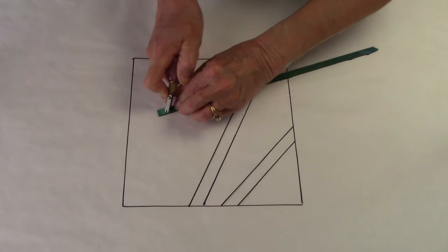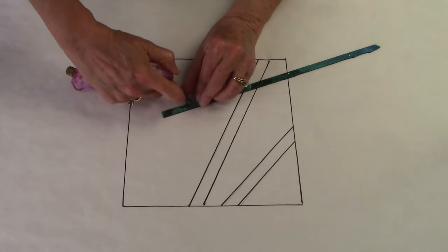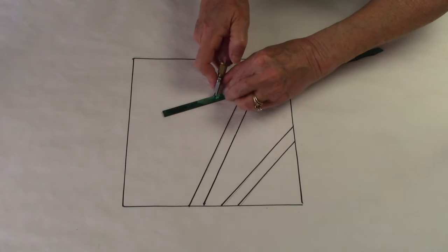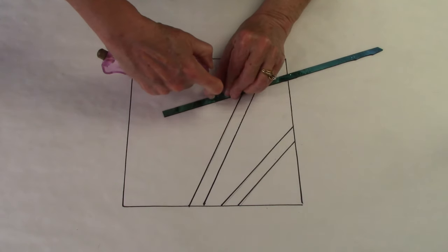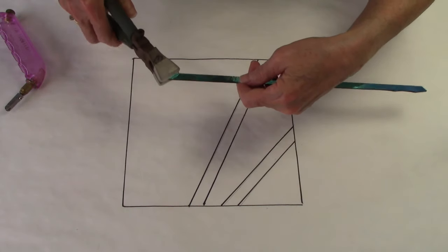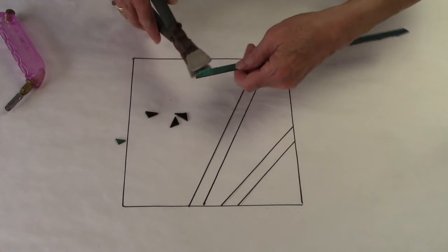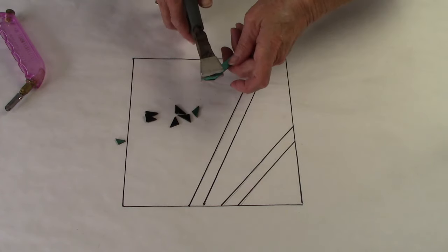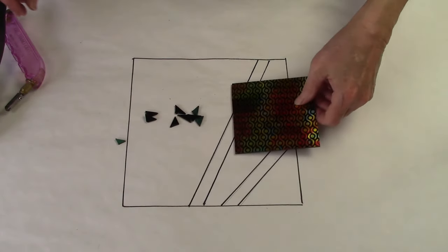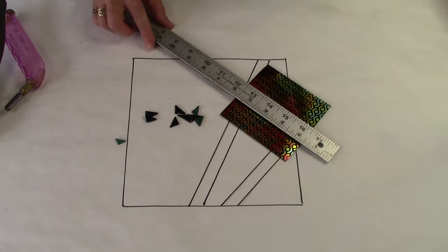Now of course I have to add a little bit of bling to my piece of art, so I cut a half inch wide strip of dichroic glass and now I'm going to cut angles to create little triangular shapes. This is a blue green dichroic on black glass, and the cool thing about this is when it melts down into the glass below it, that black layer that's underneath the dichroic will kind of spread and outline each of these individual pieces with a black line. It adds a nice attention to detail, a little additional design aspect that really is cool and gives the design another sense of depth.